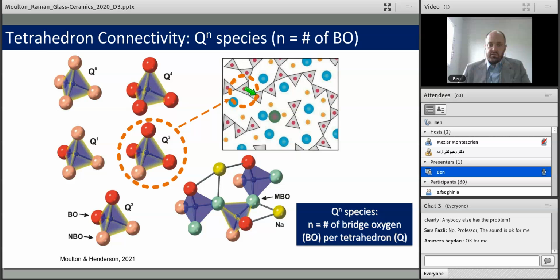One of the topics that's become really important, or potentially important, in the last 5 years, say, is that these bridging oxygens, while they have a -2 charge, and so we would think of them formally as, when they're shared between 2 tetrahedra, that their charge is balanced. Actually, in minerals, they have sodium and modifier ions bound to them. So the formal charge is less or more than 2, depending on the situation. How much of an effect this is in glasses and melts is unknown, because this has basically not been studied, though, as I mentioned, it's starting to be studied. So this is a sort of a hot topic that will hopefully lead to new insights about how to make better glasses in the not-too-distant future.